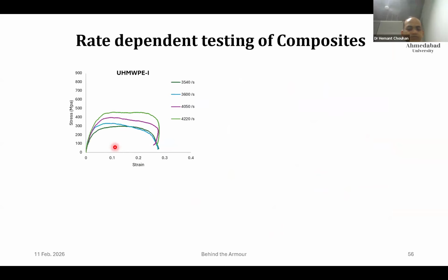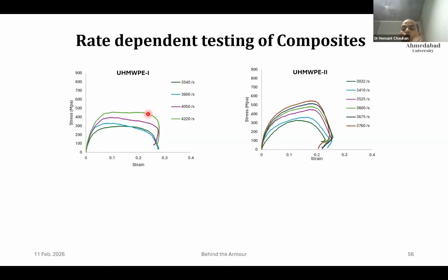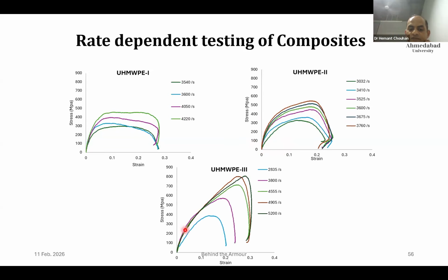These are the first generation materials, wherein there is an elastic viscoelastic zone followed by a constant plastic region, whereas in generation 2, and when I say generation, it is not by us but by the Honeywell people, they developed a better version of the fiber or the overall composite system lamina. So there is an elastic as well as plastic region, with a constant growth in the stress, and the present generation is even better than that. Here we have come down from 250 plus GSM to 144 GSM, and your material properties are constantly improving under high strain rate loading.